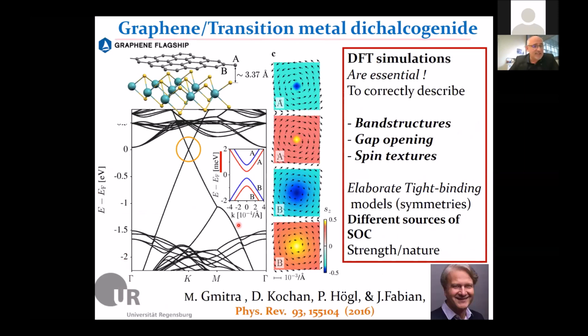And recently, the combination of graphene with strong spin-orbit two-dimensional materials like transition metal dichalcogenides has shown really unprecedented properties that I will illustrate in the next slide. In order to capture the physics of this van der Waals heterostructure, it is essential to have a very fine description, using DFT calculation, of the effect of this interaction on the band structure, but also on the spin texture, because it turns out that spin texture will completely pilot all the spin properties of graphene. The advantage of this interaction also is that, as you see here in the calculation by the group of Jaroslav Fabian, the graphene bands remain located in the gap of this TMD.